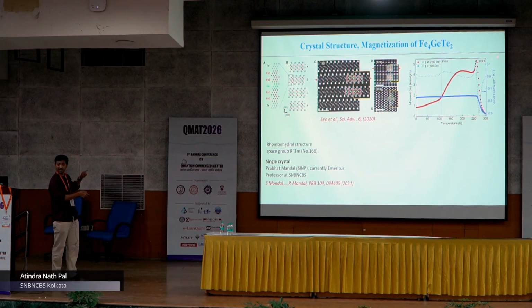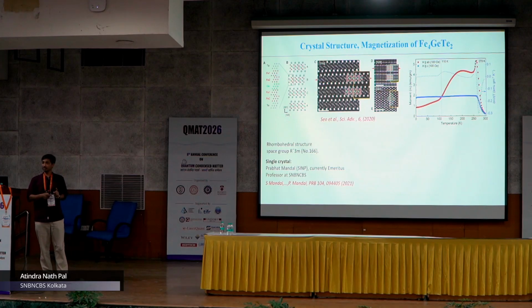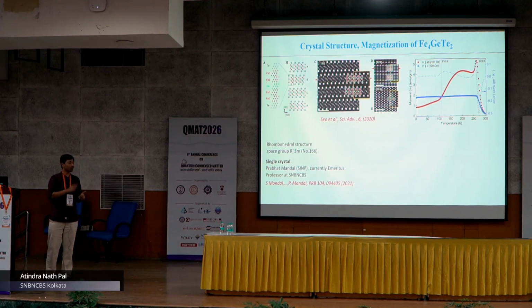And this is the magnetization measurement when the magnetic field is applied in plane, the red curve, and the blue curve is out of plane. So if you reduce the temperature, very interestingly you can see that magnetization actually decreases, and then after some point, around 120 Kelvin or 110 Kelvin or so, there is a change of magnetization, like magnetization in the C direction goes above and magnetization in the AB direction goes below. These are not simultaneous measurements, they were done one after another.